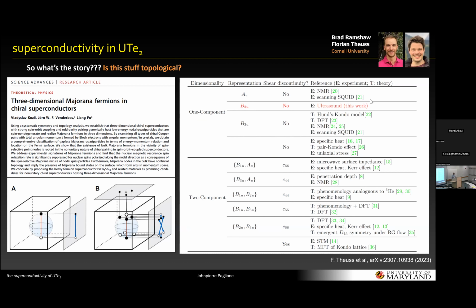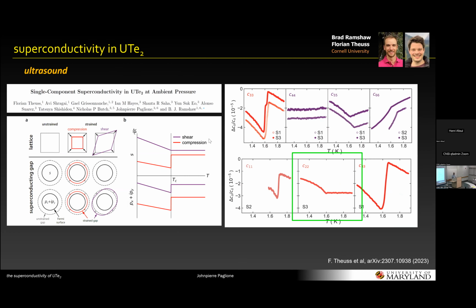And here's the answer right here. This recent ultrasound work that we worked with him on suggests that it's actually one component. And that's not only for the 2 Kelvin TC samples, but even the samples that show a double TC. So you can see here these solid points. This is a C33 measurement through TC. These are 2 samples, and one shows the double transition right in the data, and the other one shows the single. So the key data is actually in the shear elastic constants, where these 2 samples are measured, and you don't see any jump in the shear constants. So that puts a pretty strong constraint on whether there's a 2-component or 1-component order parameter. And the conclusion would be that it's a single component.